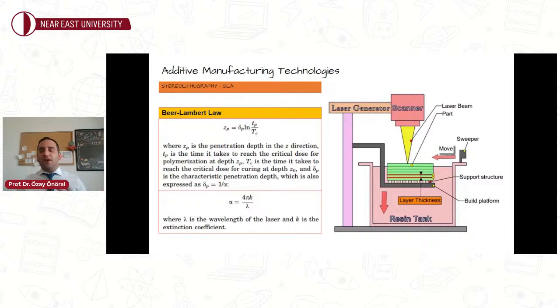You may ask why I'm trying to explain such formulas and making all the procedures complicated, but this stage is very critical, guys. If there is a mismatch in the refractive index between the fillers and the resin, the laser light will be scattered significantly, resulting in a reduced polymerization depth. This effect can result in a previous layer not connecting to the next layer, and you can encounter delamination of the layers, unfortunately. And why is this important? This plays a critical role in the material preference. I'm going to show you a slide in the next slides and explain why the material preference is so critical at this point.